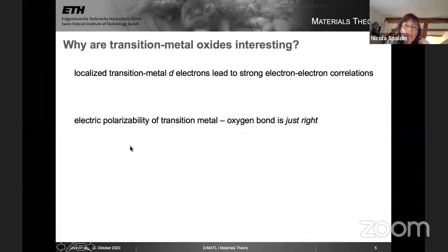From a physics point of view, there are 2 aspects that make transition metal oxides particularly interesting. One is coming from the transition metal and one from the oxygen. And from the transition metal, these d electrons, which we know are rather localized electrons, they're rather tightly bound to the nucleus, to the ion. Unlike s electrons, which are rather large and floppy, the d electrons are kind of close in to the nucleus. And this fact leads to strong electron-electron correlations.